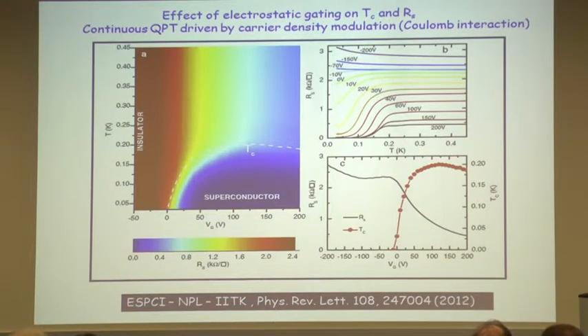I can draw the phase diagram. So this is TC versus gate field. And you can see that roughly when I'm in the positive gate voltage regime, I start seeing the superconducting state with a typical dome. Maximum TC, in this particular case, is about 0.2 K. But the maximum you can go up to is about 3.3 Kelvin.